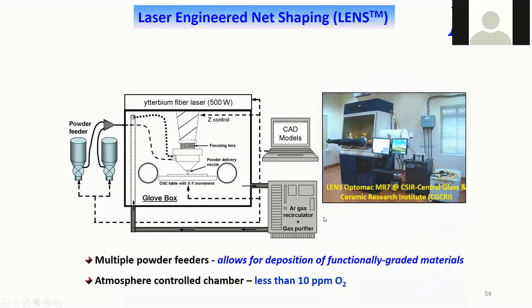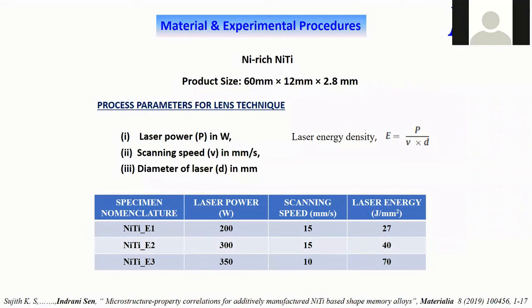Okay, so this is the system that we have used. The entire thing is done inside a glove box so that there is a controlled atmosphere. And what we again have control over in the case of additive manufacturing is that we can control the laser power, the scanning speed, etc. Based on this, we are actually controlling the laser energy density. So during the process itself, we can control the laser energy density.